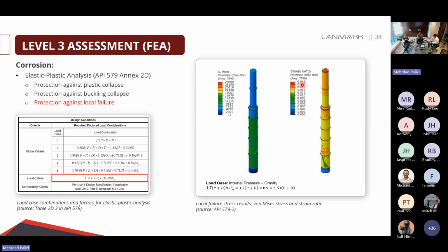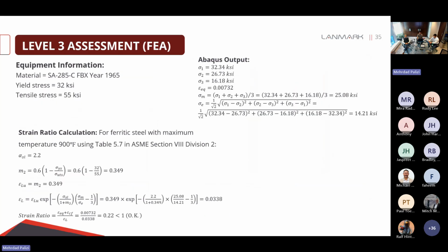We're going to get the maximum value. If the maximum value was less than 1, that means our structure is safe against local failure. But what is that strain ratio? That's strain-based failure criteria. It is a strain ratio. It is basically a demand divided by capacity. The demand is equivalent plastic strain. Capacity is something called limiting strain. So let's go through the calculation for an example, see how this is done.